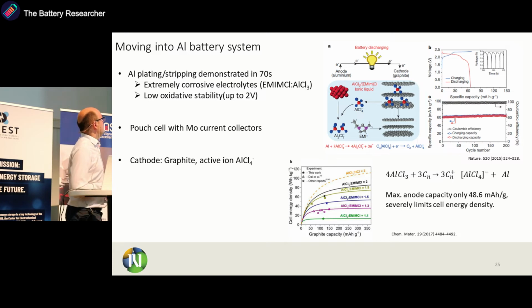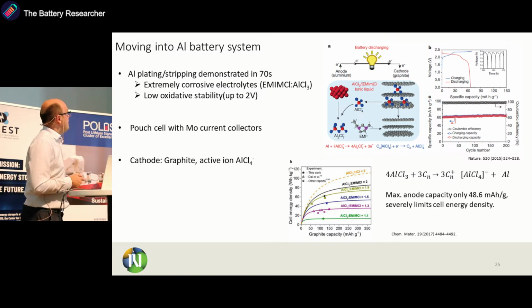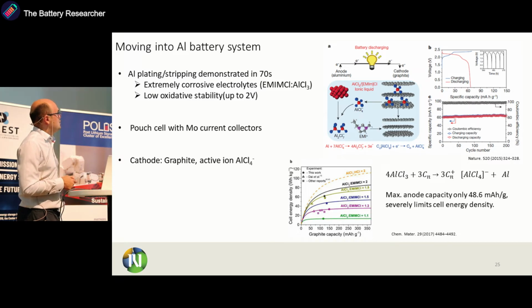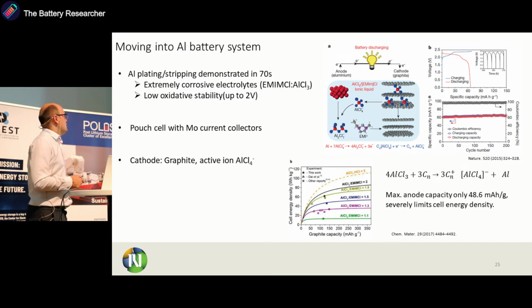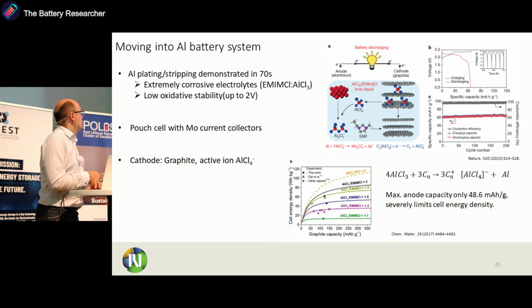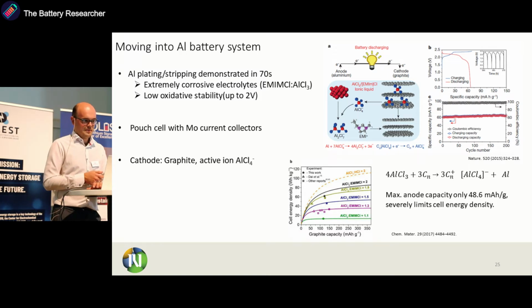And now let's move briefly to the aluminum battery system. Like I said before, the stripping and plating was demonstrated in the 70s. We basically rely on this electrolyte, which is a eutectic mixture of the ionic liquid ethyl-methylimidazolium chloride with aluminum chloride. And it has the limitations of being highly corrosive and having low oxidative stability, up to 2 volts. So we use a pouch cell with molybdenum current collectors.